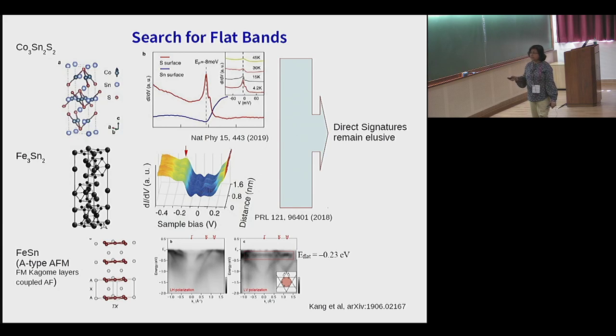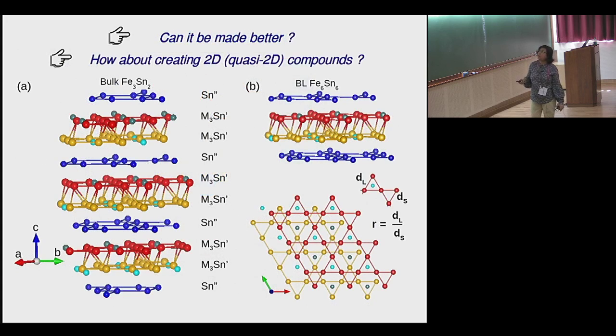There has been in recent time also this iron tin compound where there is a photoemission, and it points towards this flat band, but this flat band is several hundreds of meV away from the Fermi level. This is not really at the Fermi level. So can the situation be made better? And what we suggested is, can one create 2D compounds out of these layered compounds? So the structure is the following.